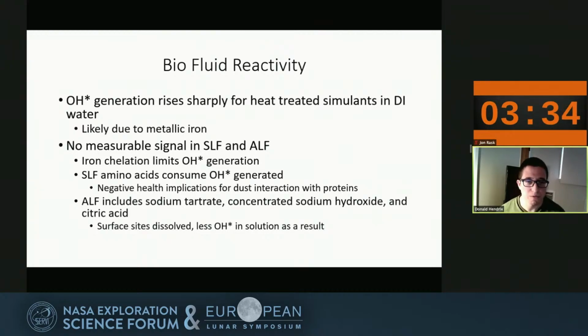And so first, we saw in DI water that heat treatment and reduction leads to a sharp increase in the reactivity, and that's very likely due to the presence of metallic iron. So there was no measurable signal in the simulated lung fluid or the artificial lysosomal fluid. So the first point I have here is that it may be possible that iron on the surface of these grains is being chelated, or sort of being bound to any of the electrolytes present in both of these simulant fluids. And so if that iron is being bound, it's not able to participate in any type of chemistry that leads to the generation of OH radical.